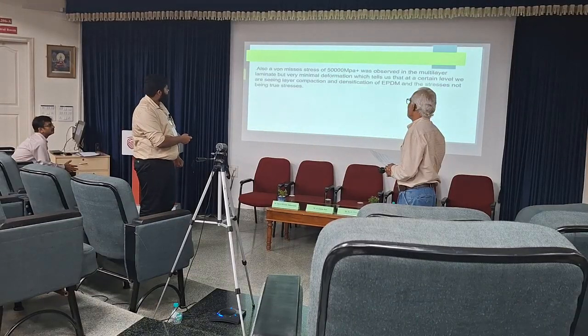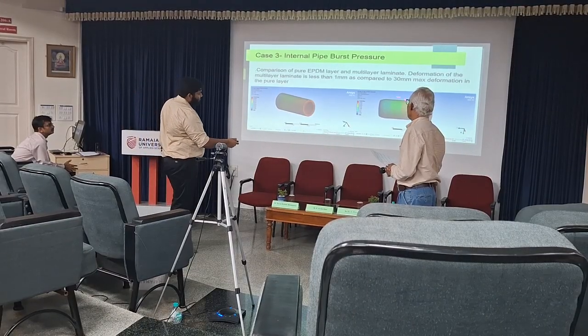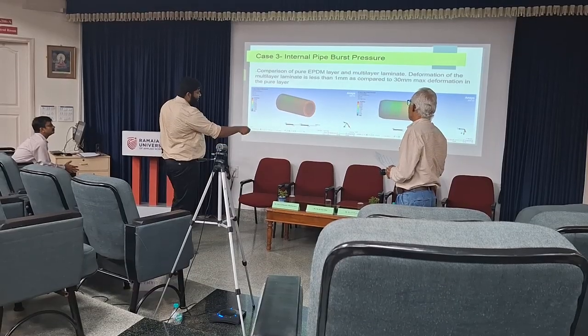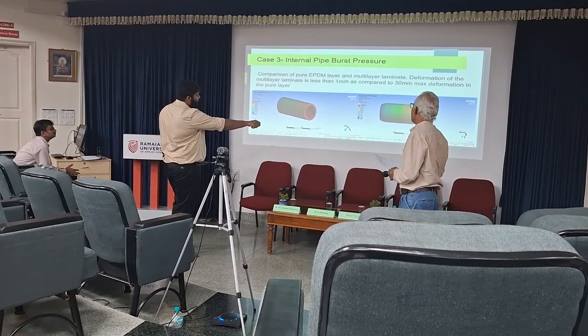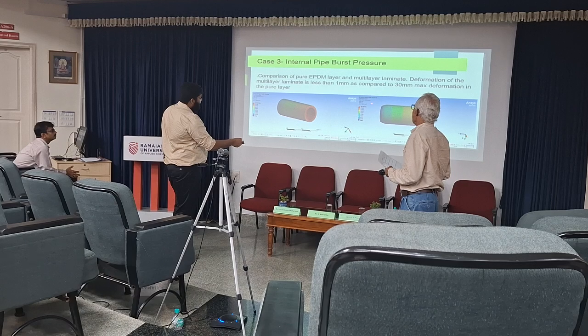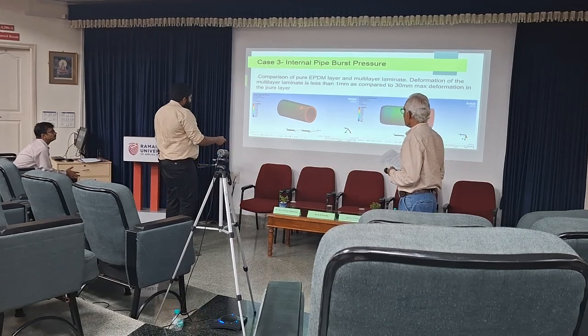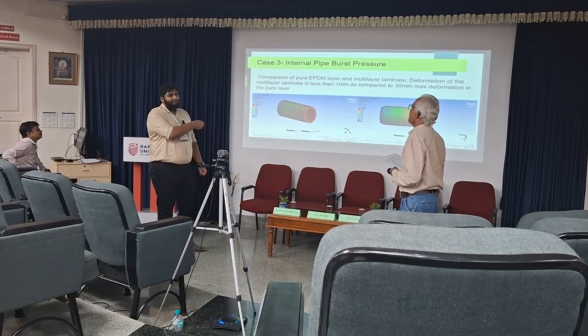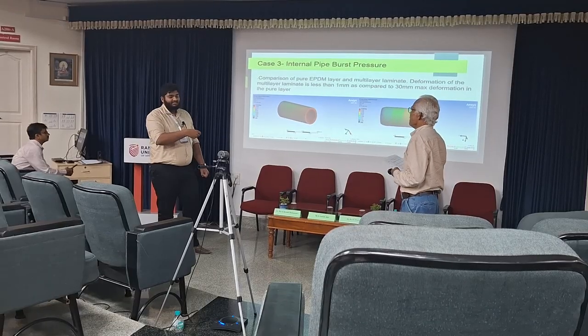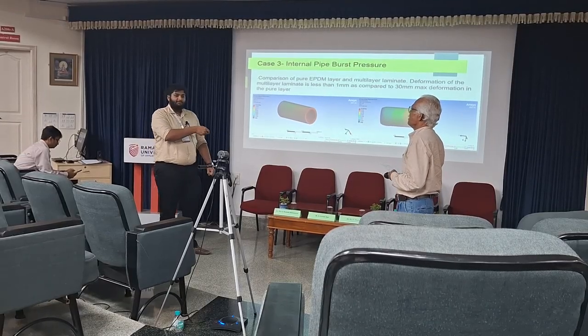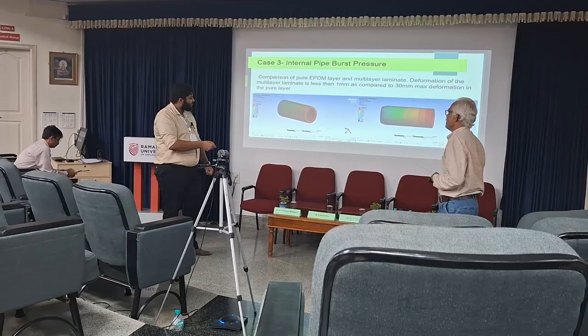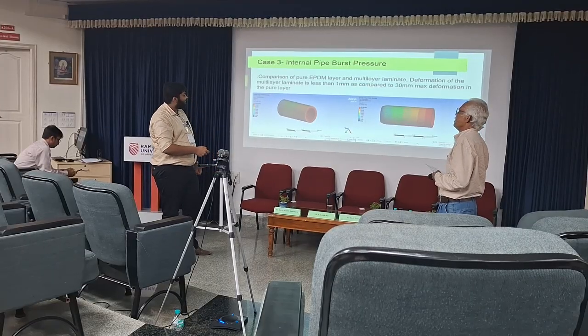So as you can see here, for the burst pressure, this is pure EPDM. Pure EPDM goes, it's not clear here, but I'll just tell you. Pure EPDM goes up to 30 mm of deformation, but our laminate only goes up to 0.9 or 1 mm of deviation, which basically supports our theory of using UHMWP and stainless steel mesh, which gives the strength to the laminate.